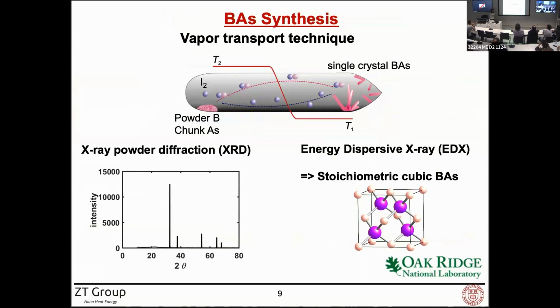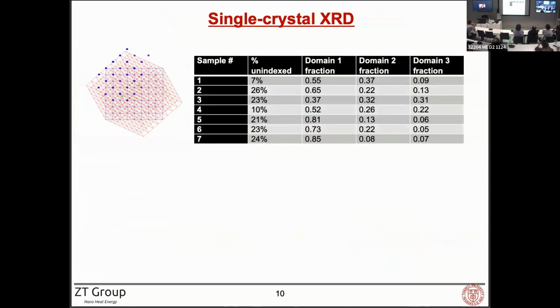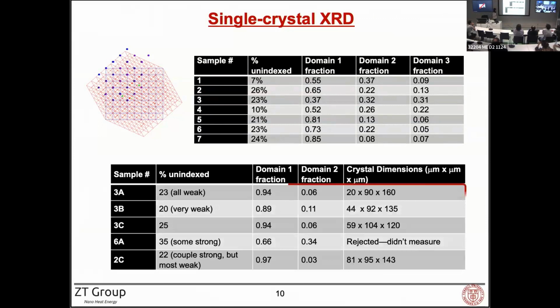All looks good. We took the sample and we did the single crystal XRD screening. And unfortunately, we couldn't really find one sample which has a single domain. So we were quite stuck. And then I said, how about we break down into smaller pieces? And luckily, we were able to identify one small piece out of sample 3, which gives us the majority of a single domain. And the sample dimension is suitable for the X-ray measurements.